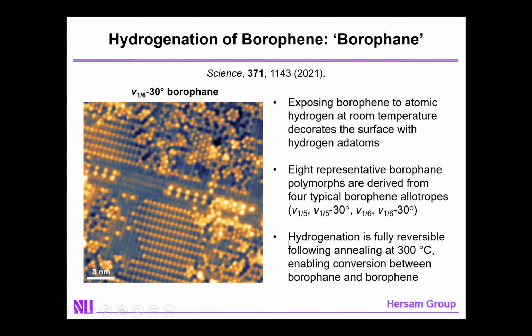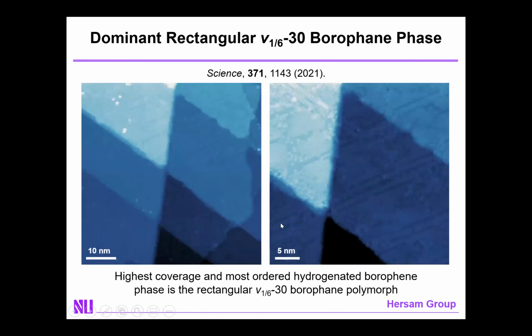I'll further note that this hydrogenation is fully reversible. You can heat this up to 300 degrees C and reversibly convert back into borophene. So this is a temporary passivation layer if you wish to remove it at some later point in time. As I noted, the dominant phase is the v1/6 30 degree borophane phase, which we can form for about 80% of the surface, and it forms a nicely ordered rectangular-like lattice.